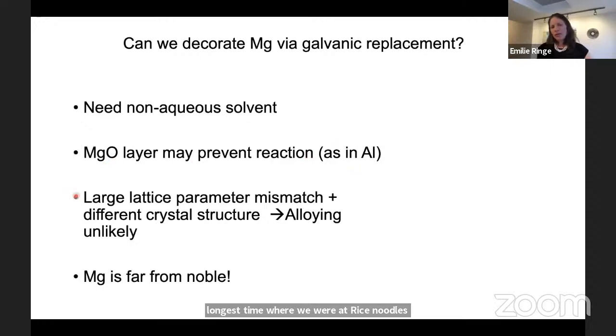There's also a problem of a large lattice parameter mismatch. We typically do galvanic replacement with metals that are miscible and that can basically epitaxially grow on top of each other. For silver and gold, you get an alloy. This is great. This is just not going to happen with magnesium because of its different crystal structure.